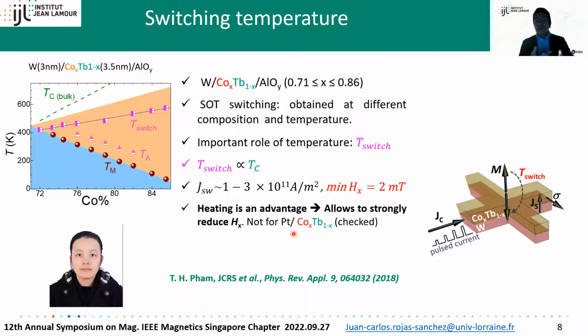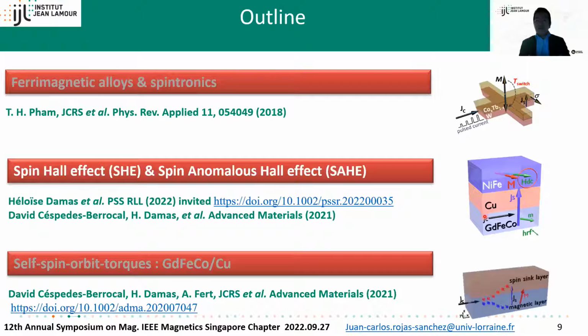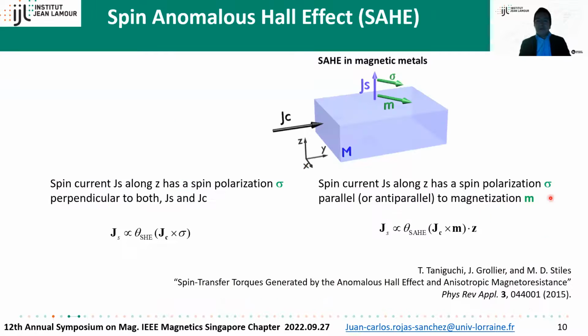I want to tell you about this system, where we use tungsten as a source of spin current and cobalt terbium as the magnetic element to be manipulated, right? But now I will show you that magnetic materials can be a good source of spin current. This motivates the theoretical work where they predict that in a magnetic material we have an emission of spin current where the spin polarization is parallel to its magnetization.